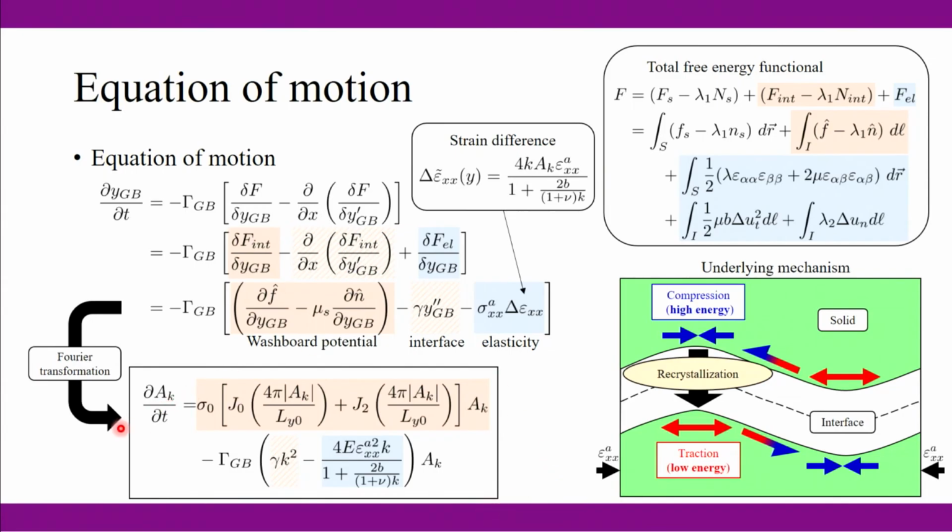So here is our complete theory, and here is a key result. So just saying the amplitude of the grain boundary is going to change over time. And they are like the two key ingredients you can see from the result here. If you see the bottom line first, this is a term that depends on the wave number. So usually we're expecting the growth rate, right? For the ATG will depend on the wave number.